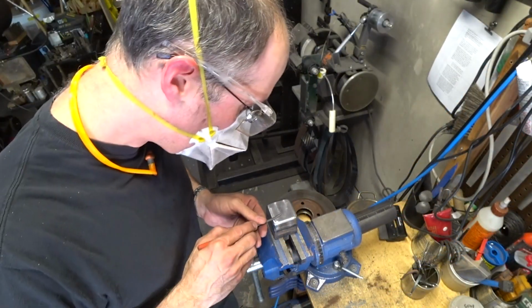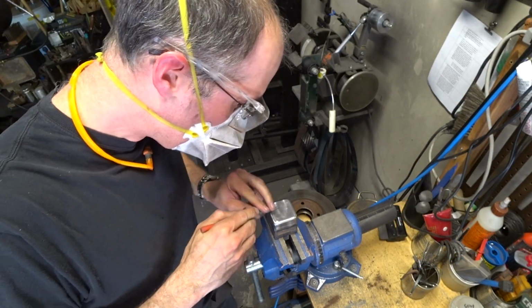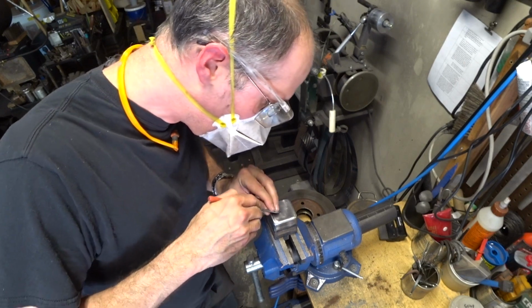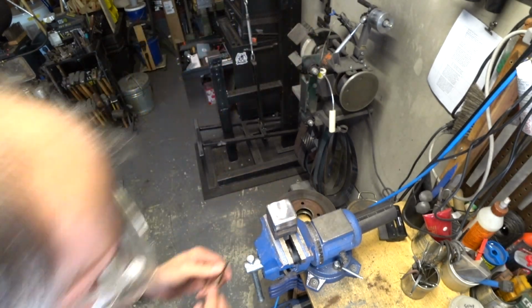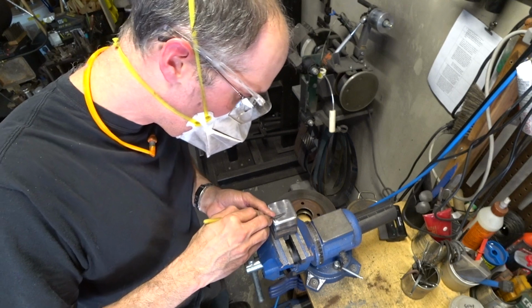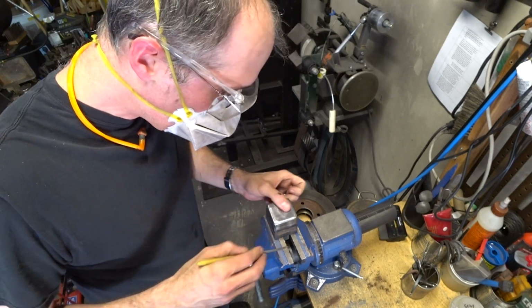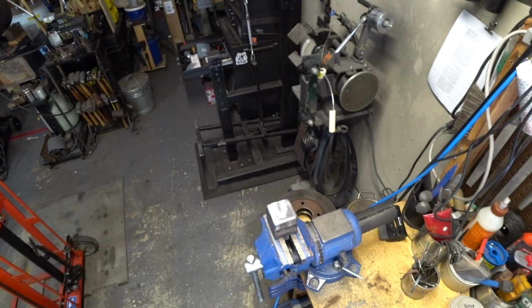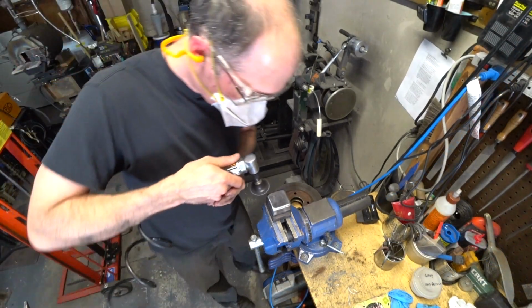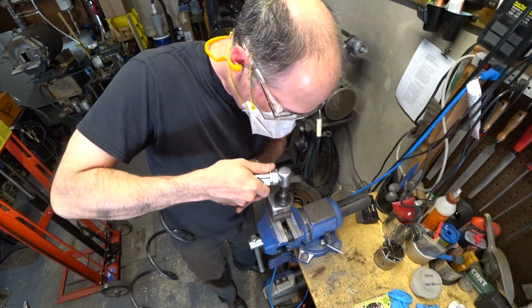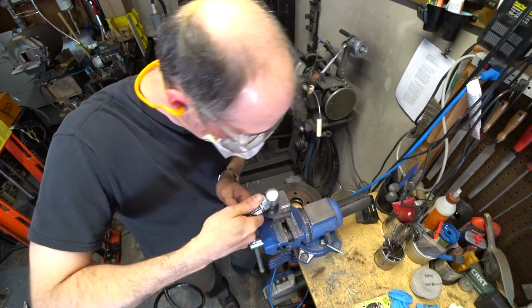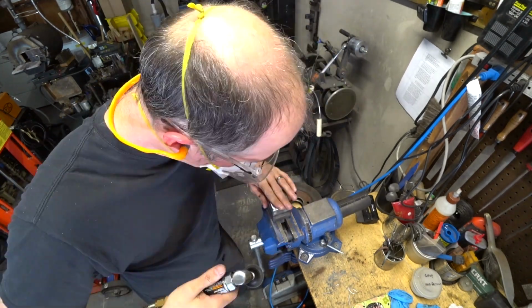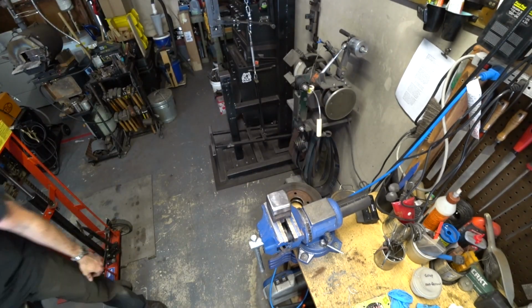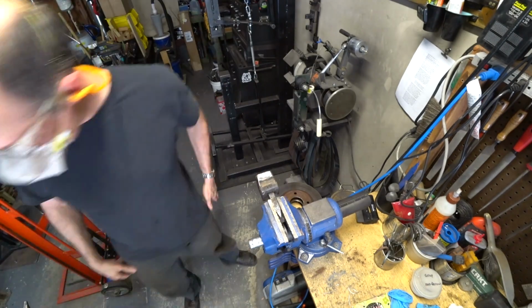The proper way to use hardness files is always to start with the hardest file and then work your way down until you're not able to scratch the material anymore. But I find this usually leaves a lot of deep scratches, so I tend to try to start with a file that's a little closer to what I think the hardness actually is, and then work from there. In the case of this anvil, I was able to scratch the surface with the 60 and then just barely with the 55, so it's probably around 55 HRC.